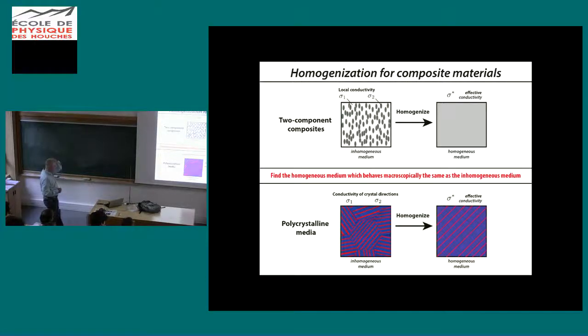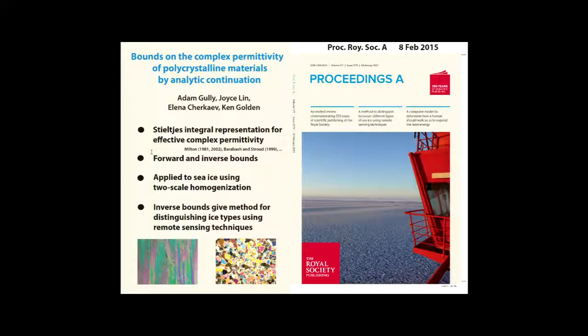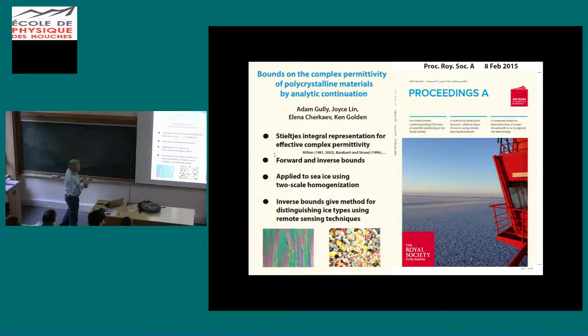I had a PhD student finish a few years ago, and we worked on this to extend this very powerful analytic continuation method to the polycrystalline problem. Namely, where we might know the statistics of the individual crystals and the distribution of their angles, their orientations in the sea ice. Then we were able to derive these Stieltjes integral representations for the complex permittivity, derive forward and inverse bounds, and then develop what I call a two-scale homogenization method to derive the bounds on the effective complex permittivity, but also to invert all that to give a new method for distinguishing between columnar ice, which is very different in granular structure, and so-called granular ice that dominates in the Antarctic, which have very different fluid flow properties.